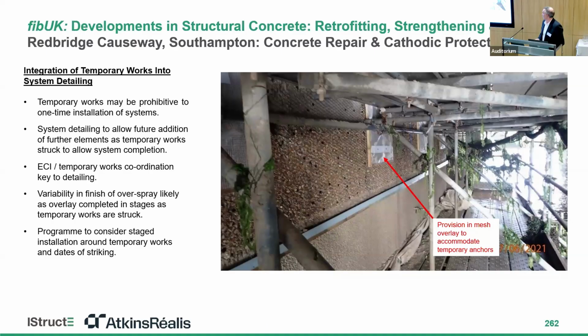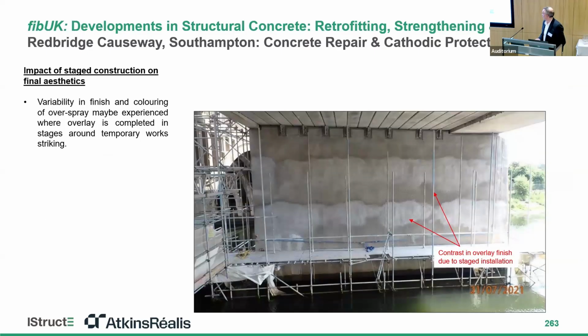This picture shows the same pier, but at the base. This is the masked off area, where the anchor plates have now been covered, ready for the overlay to be sprayed in place. And the bottom detail is what we call a tuck detail. What you don't want is the overlay finishing flush with the surface of the material, because then it can delam back up. So this tuck detail tucks the overlay into the surface, and then the detail at the bottom provides an arris on the corner to prevent spalling. And that is the finished product. You can see the overlay in different colors because of different phases of work. So some of the lighter stuff is a lot newer than the other material.